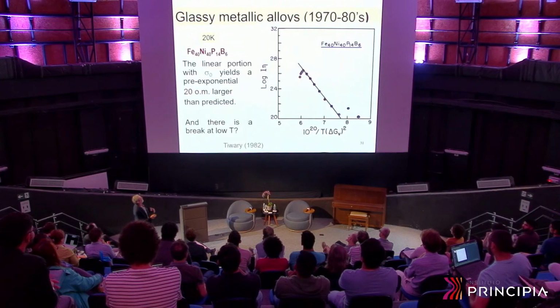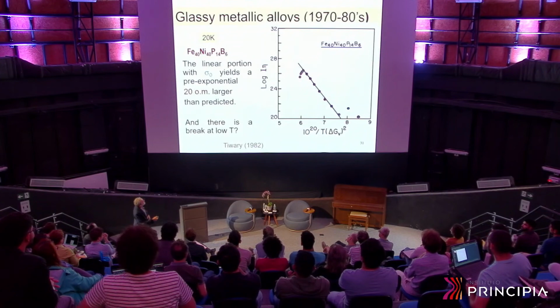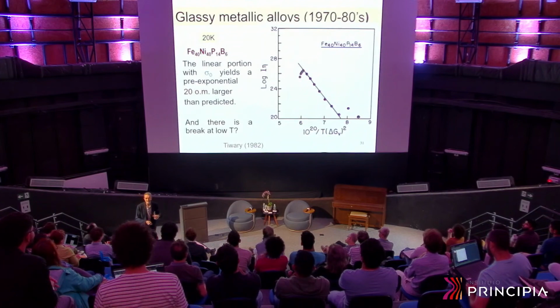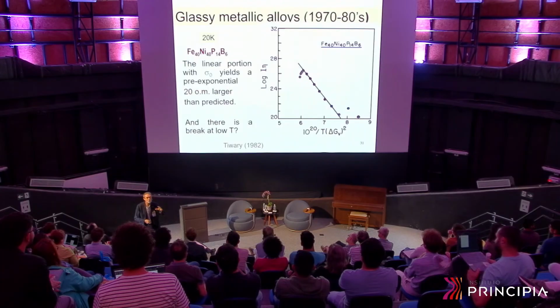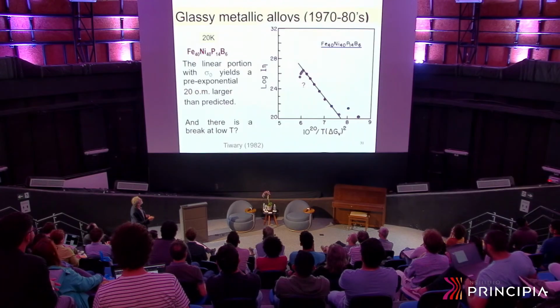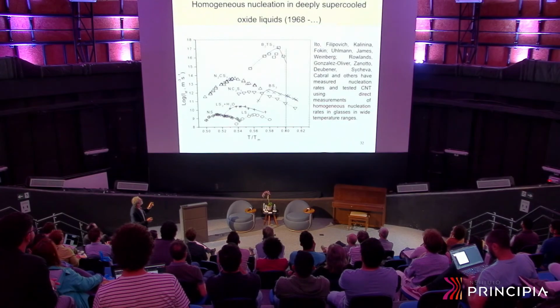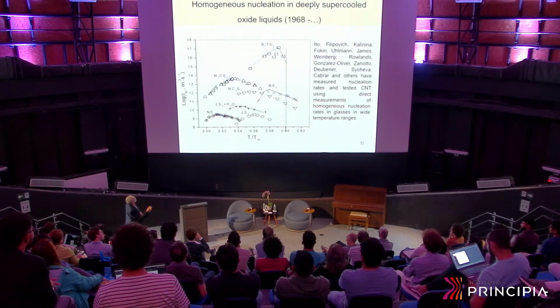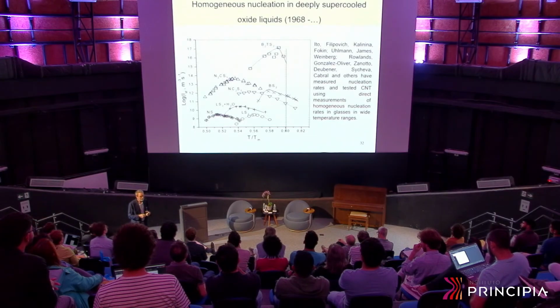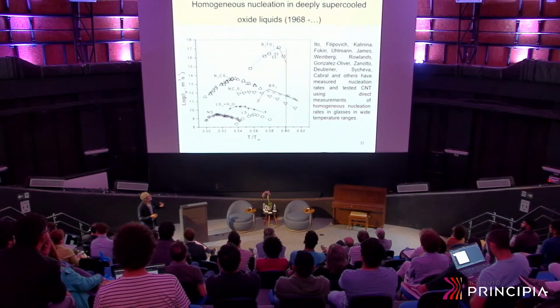Now, well, there's a lot of noise here, etc. This is not a good test. Let's do a good test. Glass-making oxide liquids are very good glass-forming materials. Metallic glasses are very unstable. So let's try to measure nucleation rates, and that's when I started to work, 1977 or so.